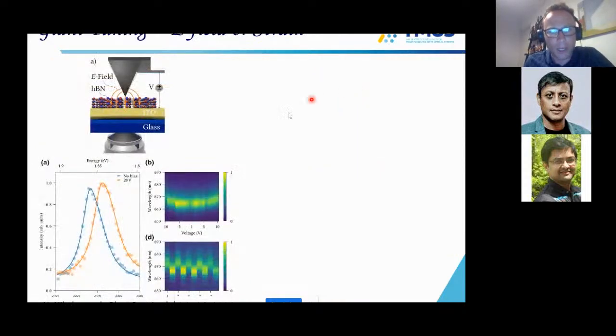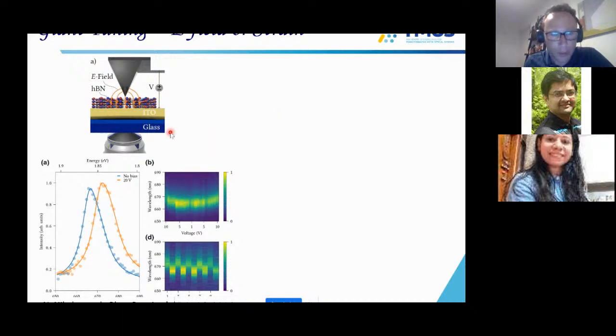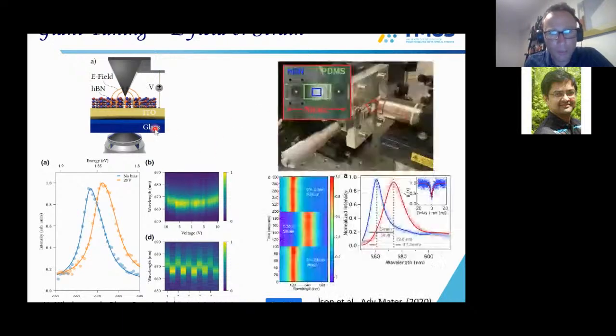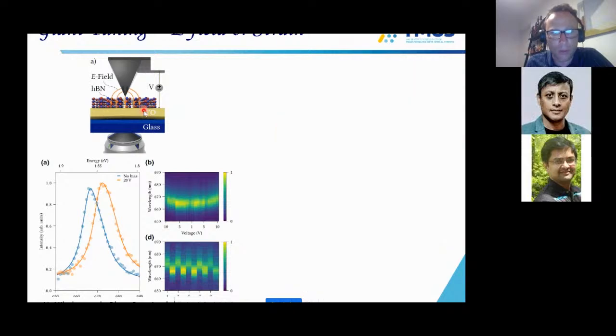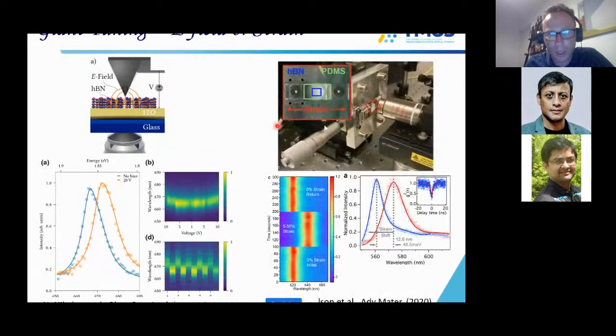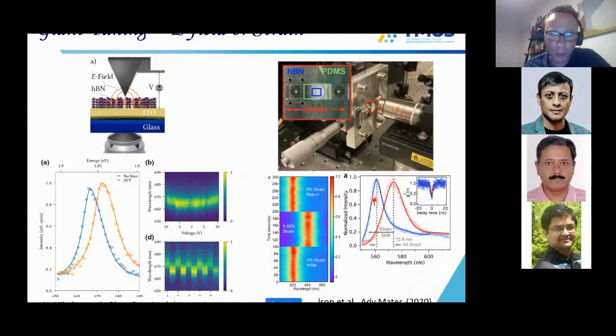So again, you can do cool experiments with that, and I will not spend much time. This is really for those of you who are entering this field. So these are just preliminary experiments of strain tuning and electric field tuning. And this is simply by taking exactly the same hBN as we grew here or on copper in the previous slide and transferring it, for example, onto PDMS or onto ITO and applying voltage or just simply straining. And you can see that this behavior is actually quite phenomenal.